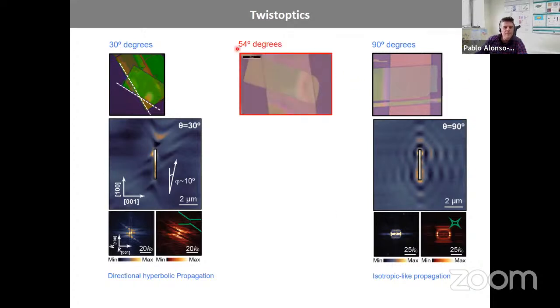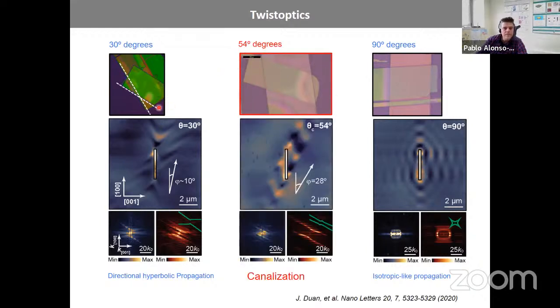And interestingly, at 54 degrees, in this case, we observe what we call canalization. All the polaritons were propagating along one specific direction, only along this direction, as if it were a waveguide. This is because, and you can do the Fourier transform of this image and go to the isofrequency curve, you have also flat bands, but these are optical bands in the isofrequency curves. And so you transit from a hyperbola, an open curve, to a closed curve, a circle or a square with another topology, through a flat band condition. And this flat band condition is very particular because it gives rise to this kind of directional propagation. Why is that?